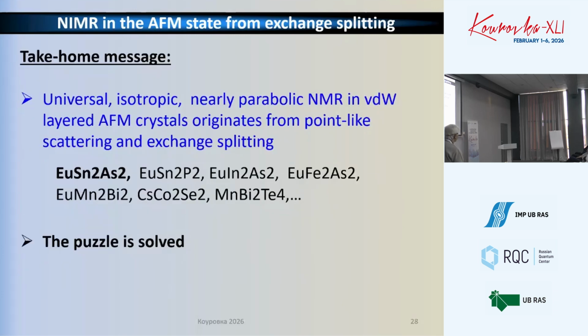Now, just for young people here, I wish to stress that this universal, isotropic, nearly parabolic magnetic resistance originates from point-like scatterers and exchange splitting. I believe that the puzzle is mainly solved. Well, of course, we can add second-order corrections to this naive picture, add magnons and so on, just to fit experimental data precisely to the theory, but it is not very interesting. And I listed here a few materials where the same effect can be explained. So I believe the puzzle is solved.